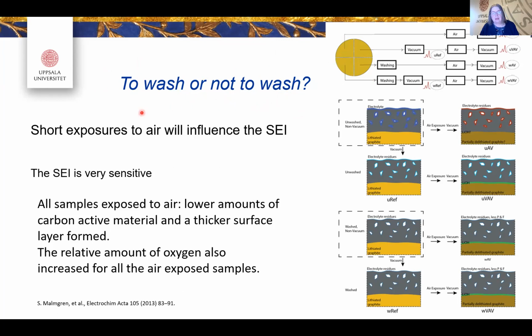And of course, does it matter if you expose your electrode to air? Will that influence the SEI? And we can say that the SEI is very sensitive, and by checking this kind of protocol where you check washing versus non-washing, vacuum versus air, we have learned that even a short exposure to air will influence the SEI quite dramatically. So all samples exposed to air, in this case it was 4 minutes, like moving the sample from a glove box into the spectrometer, which we are not doing today. We have always transfer chambers.